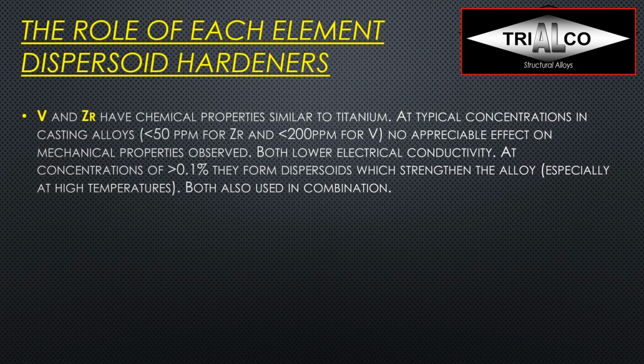Now let's talk about dispersoid hardeners, and the first ones, of course, vanadium and zirconium. We see them in some of the high temperature alloys, for example cylinder head alloys, and they have chemical properties very similar to titanium, and typical concentrations in casting alloys are very, very small, so below 50 ppm for zirconium and below 200 ppm for vanadium. There's no appreciable effect on mechanical properties observed when they're at that level.